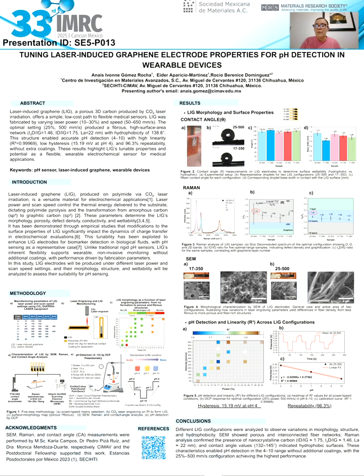The main result is for the 25% power and 500 millimeters per second laser setting, which gave high sensitivity and excellent linearity. This shows that the laser power and speed during fabrication are key to making the sensor work effectively, and it is a first step toward building a stable, reliable LIG-based pH sensor that can be adapted for more advanced applications in the future.